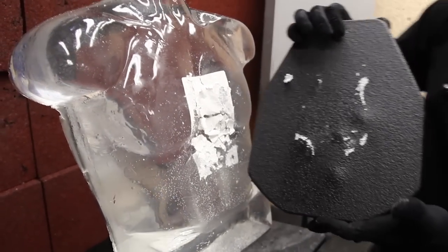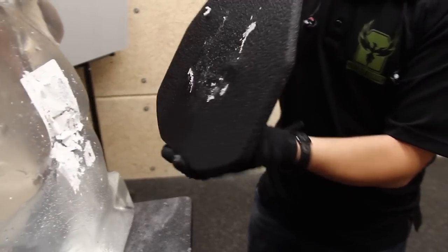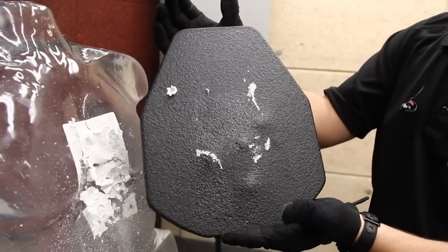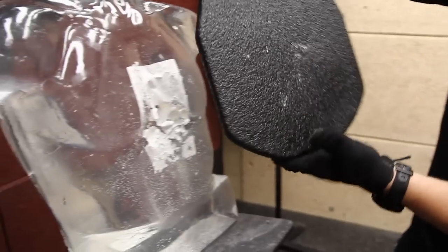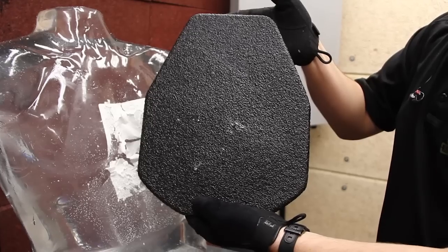No penetration. Minimal back face deformation. And full containment of all four 308 rounds at just 12 feet.